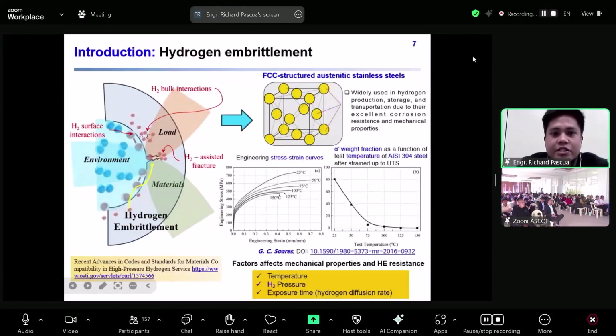However, materials exposed to a hydrogen environment at different temperatures may face some challenges, as temperature can vary the hydrogen interaction with the materials, particularly under applied stress, which can cause hydrogen embrittlement and degrade the mechanical properties and structural integrity of the material. That's why, to have a huge production of hydrogen energy, it is important to find the most efficient and cost-effective material suitable for handling hydrogen environments.